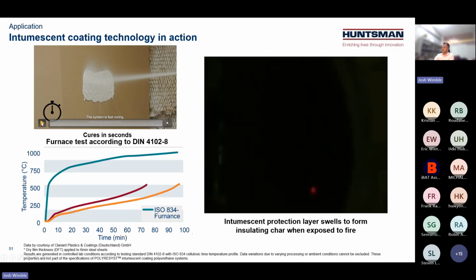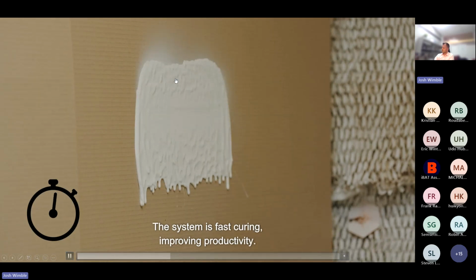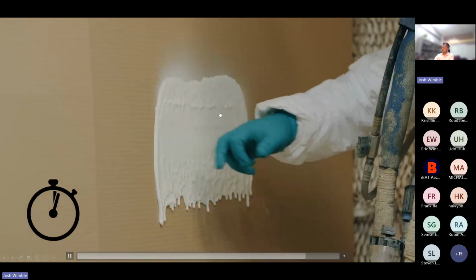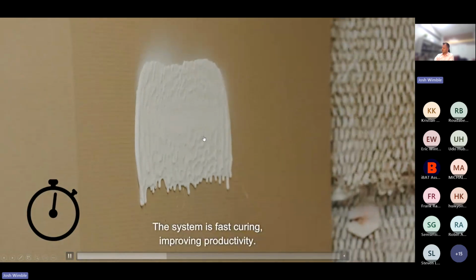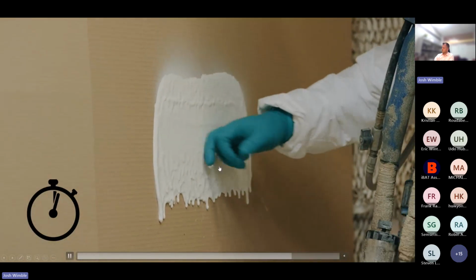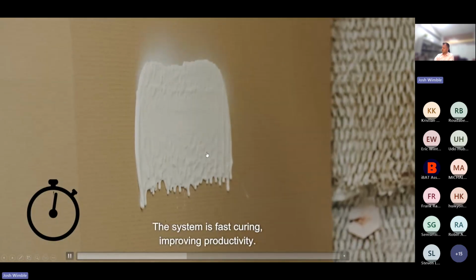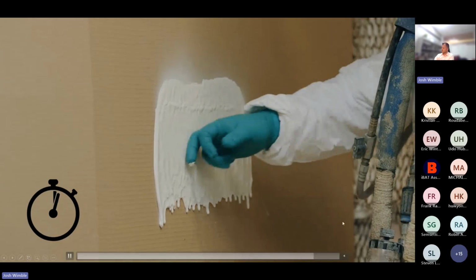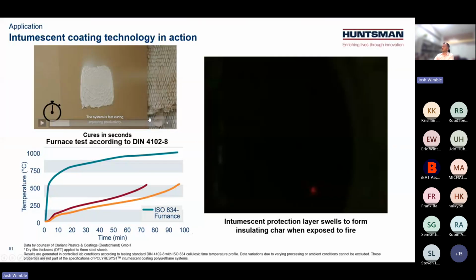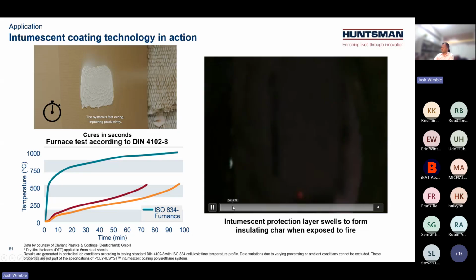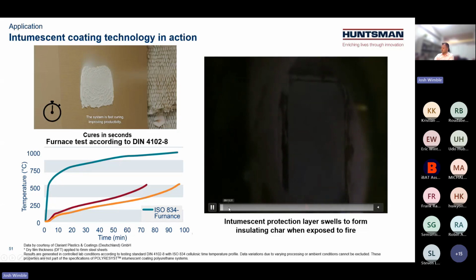So when I say fast cure, here's the spray onto a vertical surface. And as you can see, he touches it right after spray, wet, and then immediately dry, not transferring any residue after about 3 seconds. So very quick cycle times with this technology, can be sprayed into a variety of applications. I'm not going to show you this whole thing, even though it's sped up. This is still about a 4-minute video and we're near the end of our time.